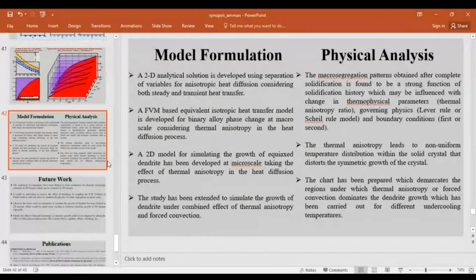Coming to the physical analysis, the macro segregation patterns obtained after complete solidification are found to be a strong function of solidification history, which may be influenced by changes in thermophysical parameters, thermal anisotropy ratio, governing physics, and boundary conditions. And the thermal anisotropy leads to a non-uniform distribution within the solid crystal that distorts the symmetric growth of the crystal. And the chart has been prepared to demarcate the region in which thermal anisotropy or forced convection dominates dendrite growth, which has been carried out for different undercooling temperatures.